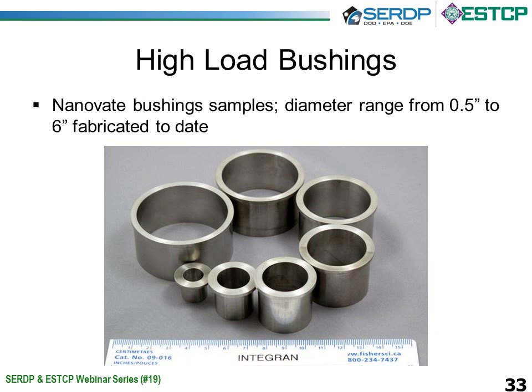We have demonstrated that you can produce a wide range of bushings. This is an example of some of the bushings that we've made, demonstrator pieces. You can see a range of diameters with and without flanges. And in fact, we made bushings up to about 6 inches in diameter to date. So you can go from very small bushings to very large bushings.